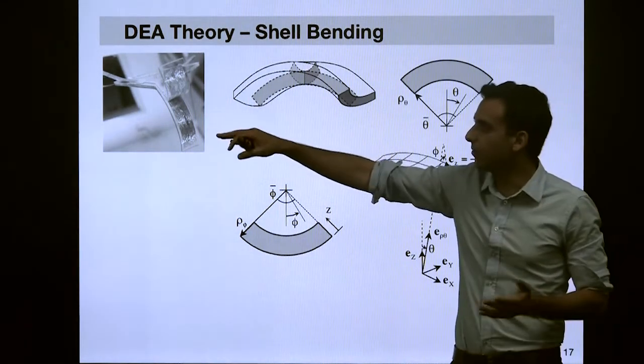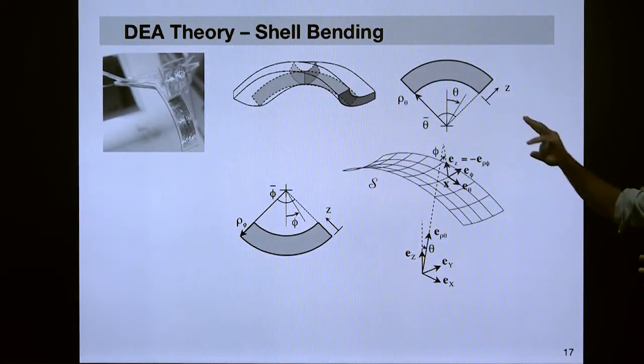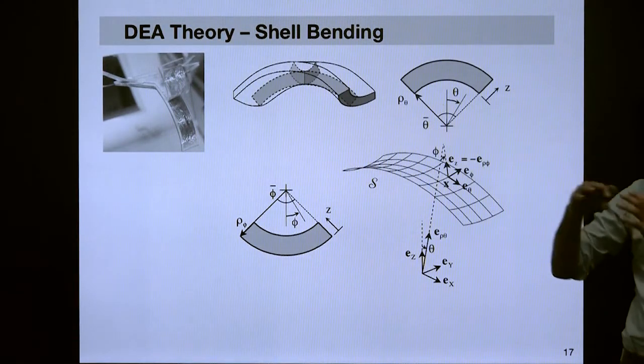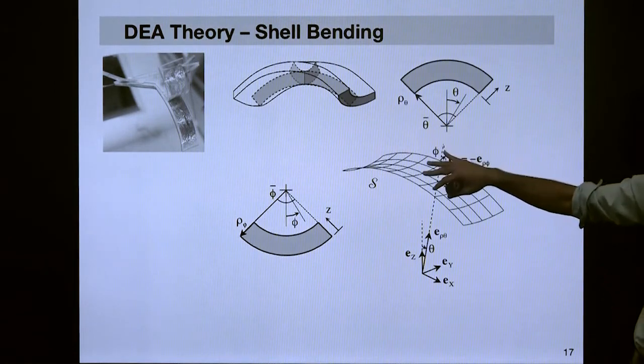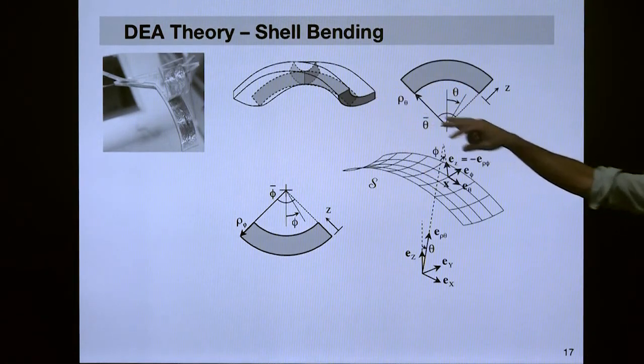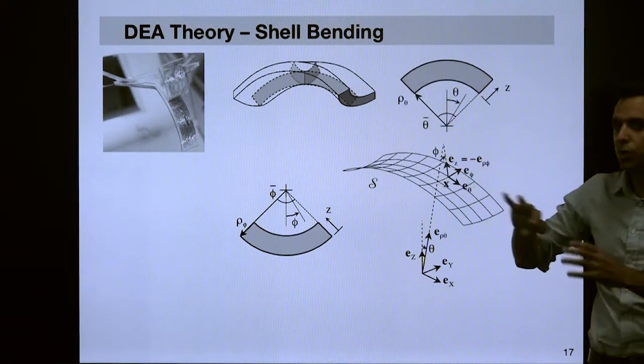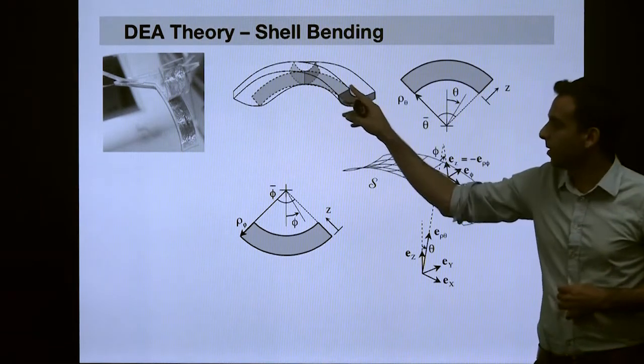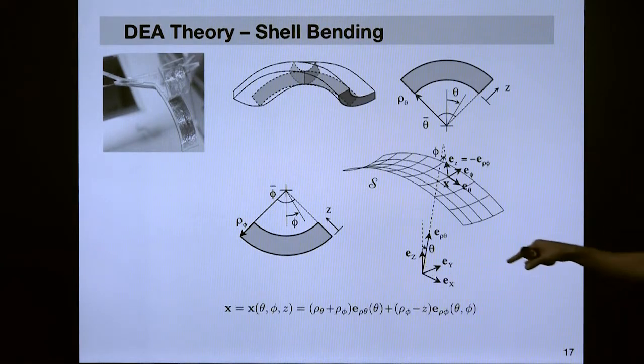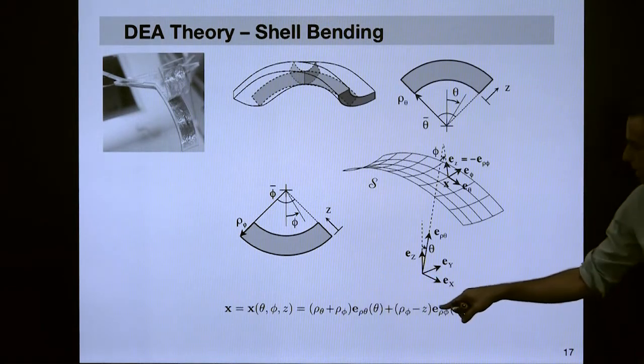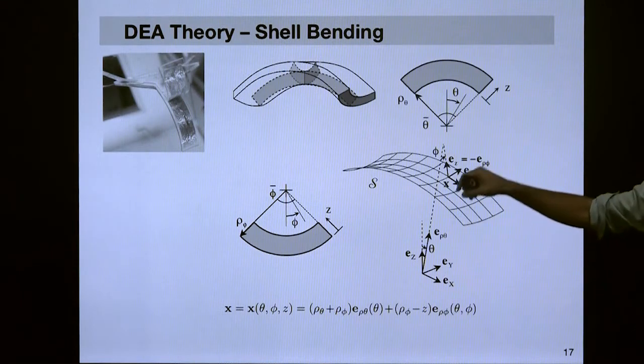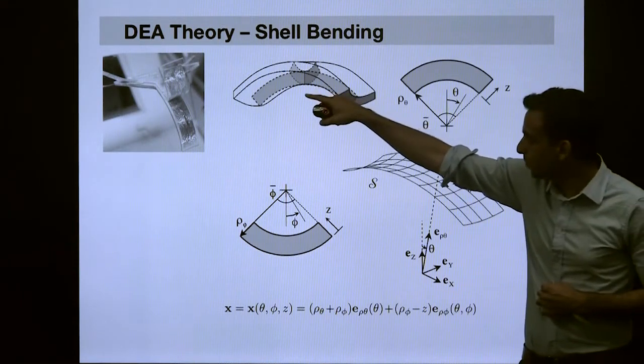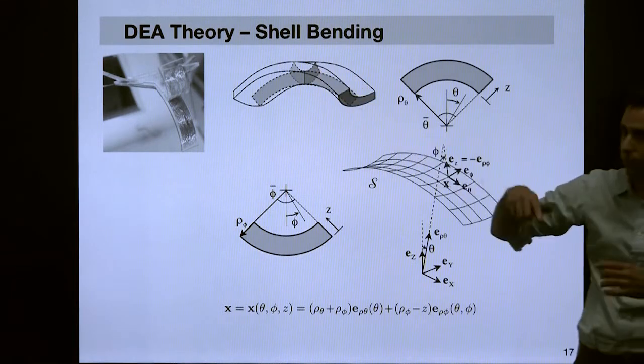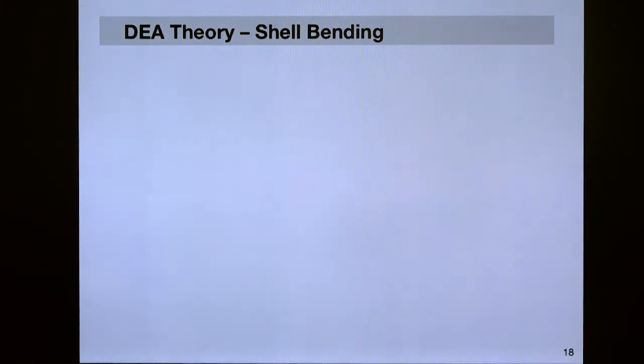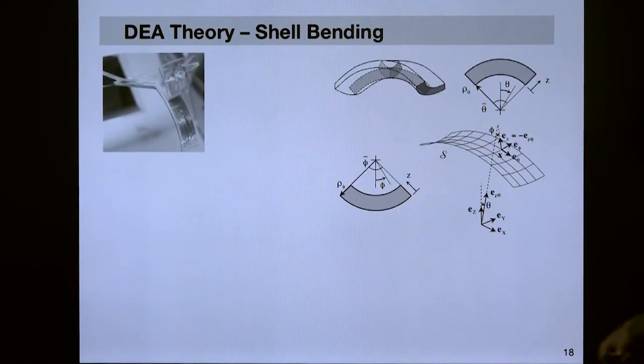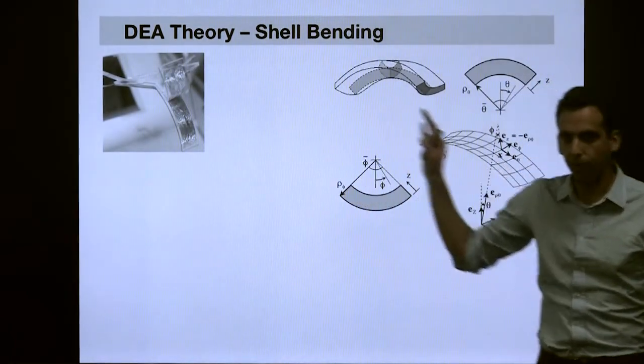And what's actually nice and a relief is that a lot of the same mechanics, a lot of those principles using the Rayleigh-Ritz technique, these variational techniques, they all still apply even for an elastic shell. The challenge now is purely kinematics. How do we represent deformation of a shell? There are a few different ways we can do this. I came up with one way of representing the position of points through the thickness of our shell as a function of these two principal bending curvatures. We can take the gradient of that deformation mapping. We get our deformation gradient. From that, we get the principal stretches.